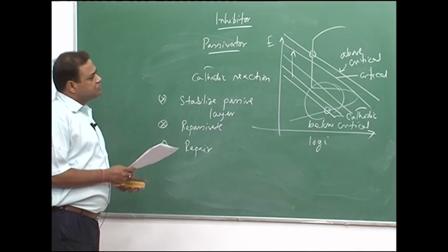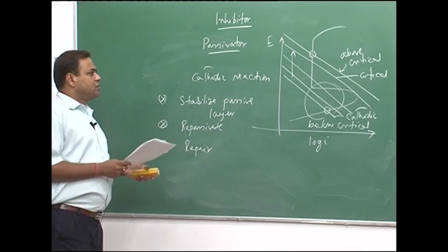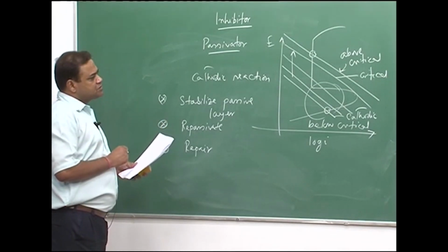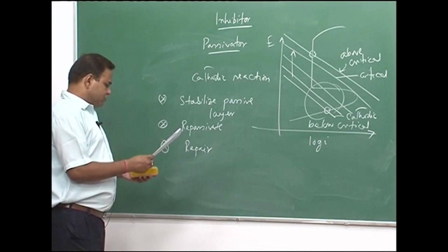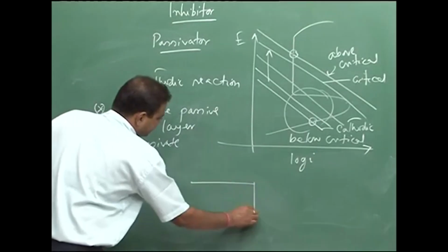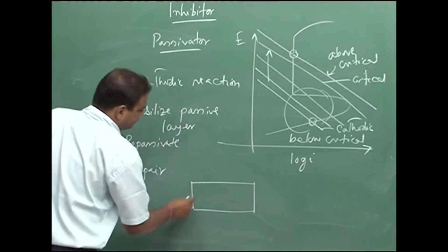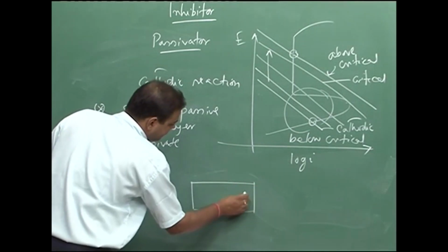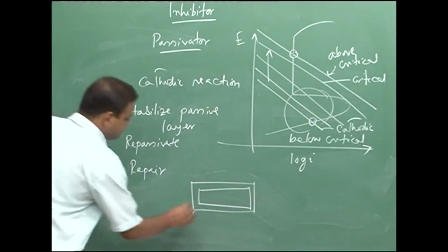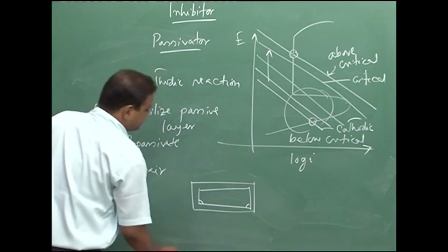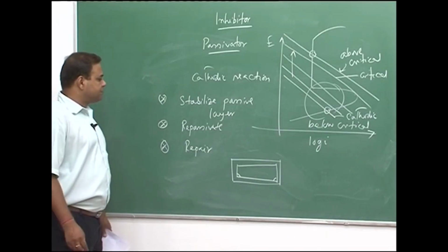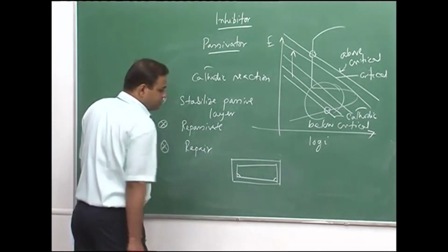whether the temperature is increasing. If the temperature increases, critical current would also increase, and also if you have the lowering in pH, critical current would also increase. So, those are the cases, and then of course, let us say you have this particular metal surface. This is a tank where you would like to use this passivator, and these are basically the dead zone where the liquid is stagnant. So, care should be taken that the inhibitor presence is there in the dead zone.